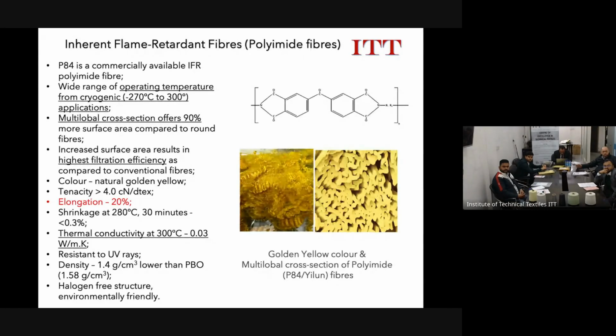And you can see thermal conductivity at 300 degrees centigrade. I'm trying to find out a lab in India which can do thermal conductivity at higher temperature. I know a few labs in the US and Europe, but they are very costly. So if anyone is aware of any lab in India which can do thermal conductivity tests at higher temperatures, at 500, 600, even I have a requirement where I have to test thermal conductivity at 800 degrees centigrade. And these are the things we need to see.